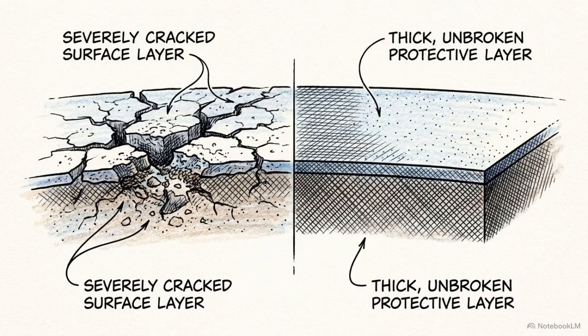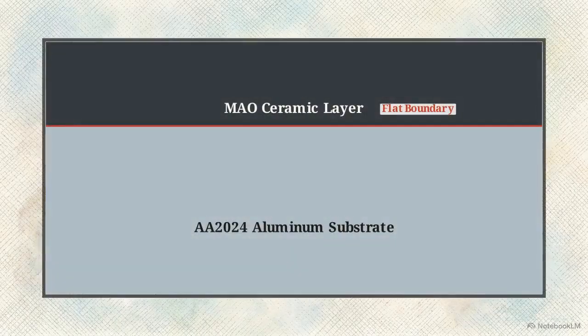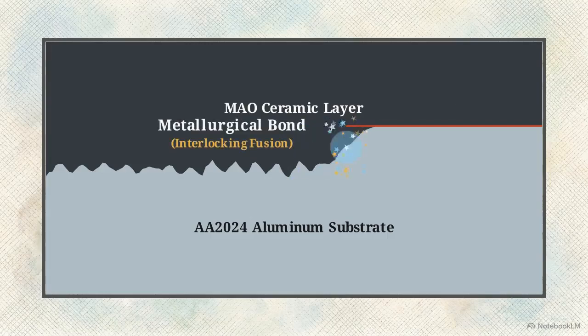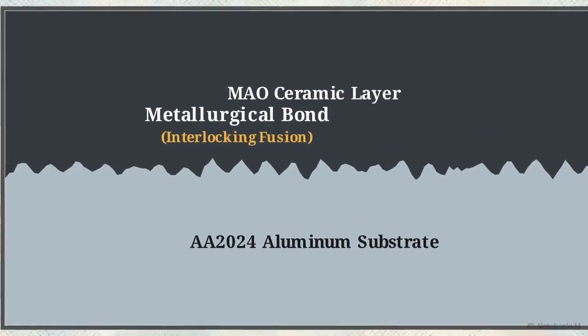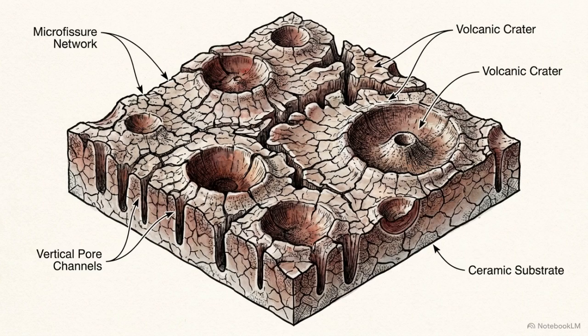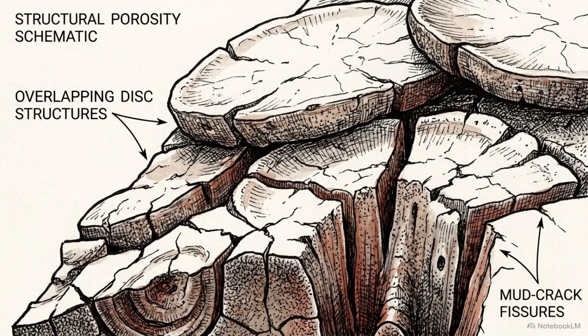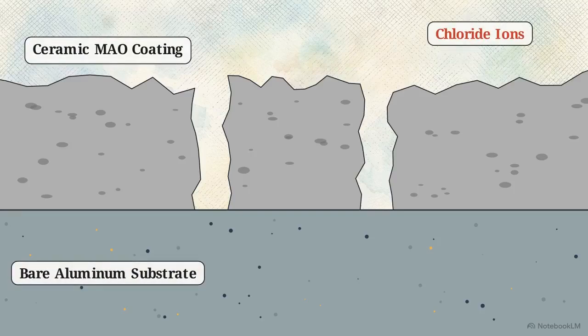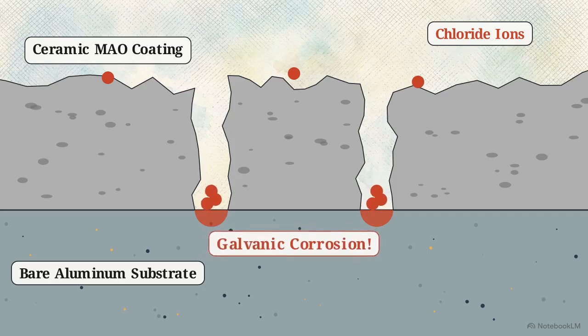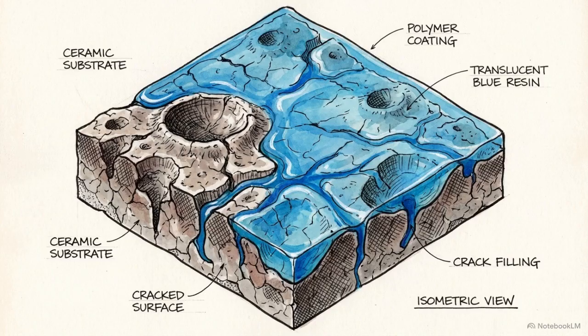MAO overcomes the failure modes of standard anodizing by using plasma discharges to drive the uniform growth of a metallurgically bonded ceramic layer. While the MAO process creates a hard barrier, the plasma dynamics leave behind an inherently porous, cratered morphology. The resulting ceramic surface is characterized by microscopic mud cracking and a pancake-like structure. This porosity is a critical flaw. Corrosive chloride ions can travel straight down these open vertical channels to reach the bare aluminum substrate. Solving this requires sealing the porous oxide structure with a complementary polymer matrix.